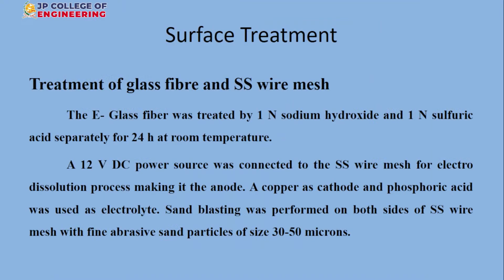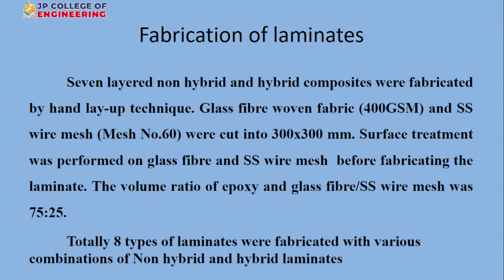So we made some surface treatment in order to improve the bonding. That's the idea. Already the glass fiber comes with a silane coating, but instead we checked whether going to a very mild acid or a mild base helps. It's a very fine filament, so it should not be affected, otherwise it will be deleterious. So we go for careful surface treatment with mild reagents. Similarly, we did some surface treatment for the stainless steel mesh, and by doing so we can improve the adhesion between the resin and our item. That's the idea.